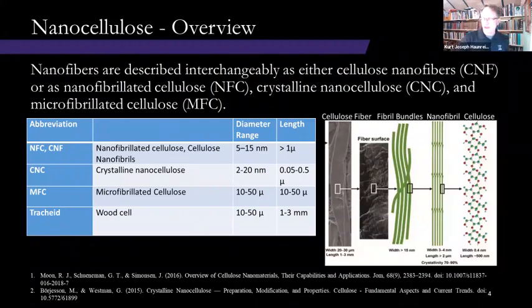I didn't mention this in the presentation, but the other clue to look for is in microscopy. If they claim they can see it with an SEM, then it is not nano. Even though you might think scanning electron microscopy has to be at the nano size, the problem is that when you do SEM, you have to coat the material with platinum.